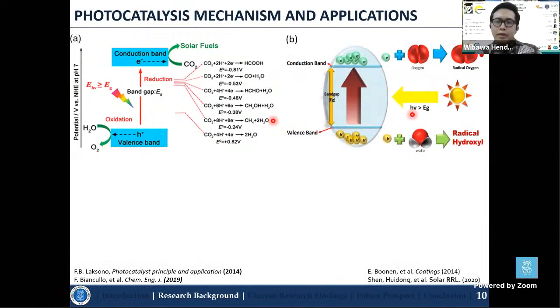In addition, in the case of wastewater treatment or organic pollutant oxidation, the electrons and holes generate reactive oxygen radicals. In this case, the oxygen will react with the electrons in the conduction band to generate superoxide radicals, while the holes in the valence band will react with water to generate hydroxyl radicals. Both radicals play very important key roles in degrading or oxidizing the organic pollutants.